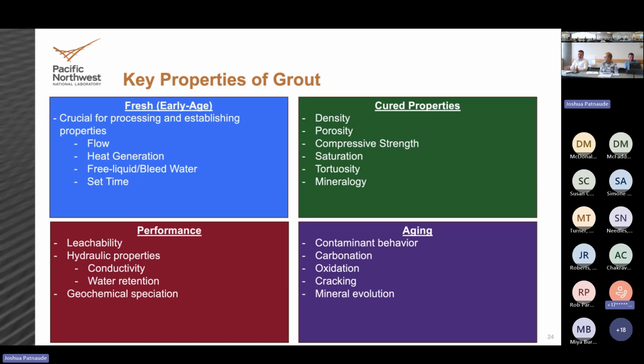And those semi-dynamic leach tests, there's a number of different ones. EPA has their method 1315, American Nuclear Society has method 16.1, ASTM has method C1308 and 1220. Everyone's got similar variants of the same technique. Take a monolith, put it in water, measure how much stuff comes out. And then we go to field exposures, where we do tests in columns in the laboratory or a lysimeter test like we have ongoing at the Hanford site right now.